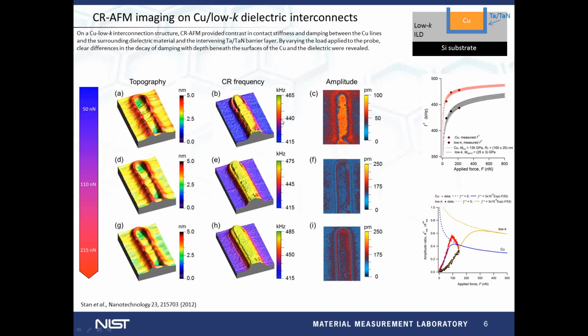If we look at the color bar scales here and the contrast, the color contrast is different at different loads. So we use copper here as a reference material and calculate the elastic modulus of the low-K dielectric material, and also we combine the frequency and amplitude measurements to look at the dissipative contribution to the tip sample contact coupling in terms of contact dynamics. So here is the contact resonance amplitude versus the applied force, and we were able to resolve the decay of damping in the nearby subsurface region of the two materials.